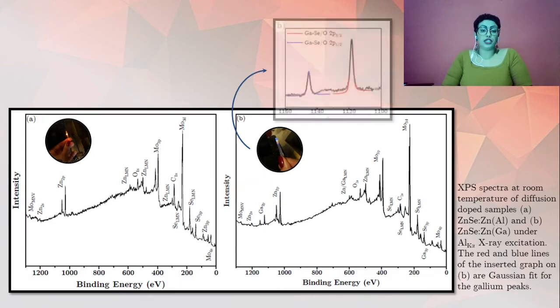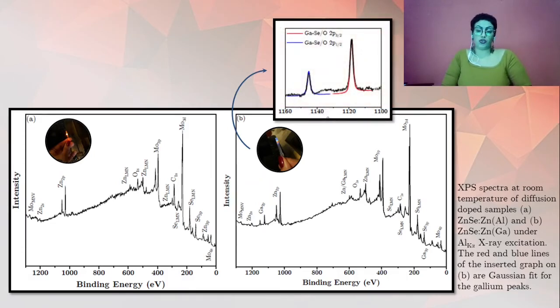The Gaussian fit performed on the peaks related to the 2p orbital of the gallium indicates that the gallium atoms are partially bound to oxygen atoms, naturally oxidized on the sample surface, and partially bound to selenium atoms, since they enter as substitutional donors to zinc in the material, as we expected.